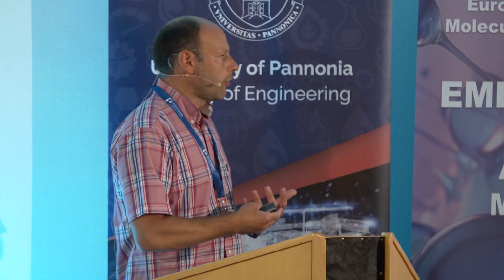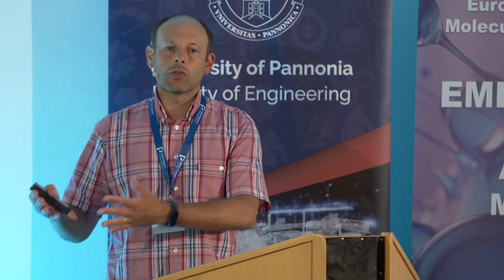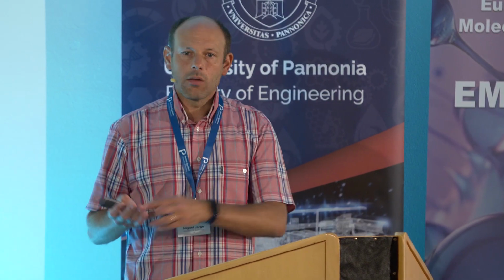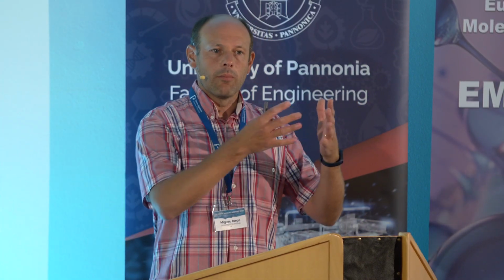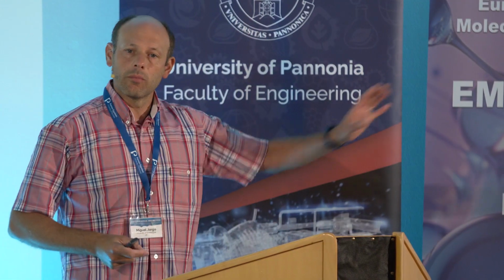The downside, of course, is that precisely because you don't have those anchors, if you move away from the conditions in which you parameterize your model, it can no longer work, okay? Or it may fail. And I've, in fact, experienced this with a postdoc I had for a while, trying to do inverse Monte Carlo of a surfactant system. And the model we got depended on which data we used to derive the coarse grained, okay? So if we tried to fit a micellar system, we would get a micellar system. We could do predictions in the micellar region, but then it wouldn't predict the liquid crystals at a later, higher concentration, and vice versa, okay? I'll show you some graphs where that is more evident.